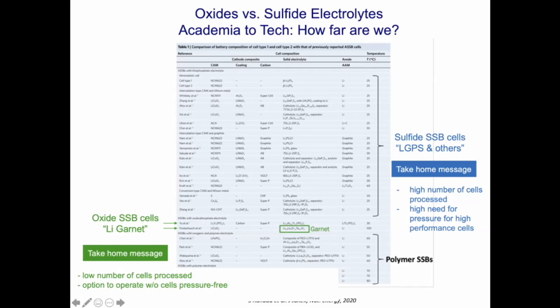And the reason for that is quite simple. Sulfide-based electrolytes, in terms of processing, allow low-temperature processing that you can fabricate quite easily. These are very soft materials, and that's quite advantageous. What's a little bit challenging with sulfides is that you need very high pressure on the cells to operate them in later cell geometries. Now, when we look at the oxide-based materials, they're quite interesting because they can operate with pure lithium, which is a bit of a challenge for the sulfide-based cells. And also because they are often manufactured at high temperatures and high pressures, they need less pressure during operation.